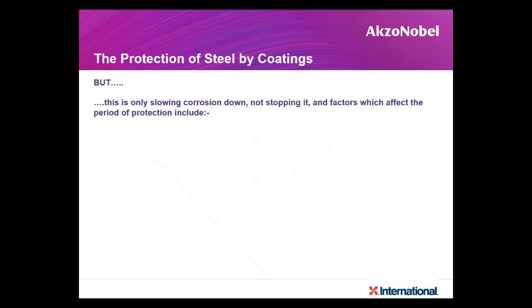Keep in mind, the life is about the process called durability. By applying coatings, what you're trying to do is protect it in the best possible way so that it slows the corrosion down. It doesn't stop it. What will affect it over a period of time is the kind of environment to which you expose it, and the surface preparation of the surface. That means steel has got a lot of contaminants. I was telling you, oil and grease, surface salts, mill scale, rust. You will have seen that on steel. Now this has to be cleaned in a proper way. That is a surface preparation process. Once you clean it properly and apply a coating, the durability increases. So it's very important.